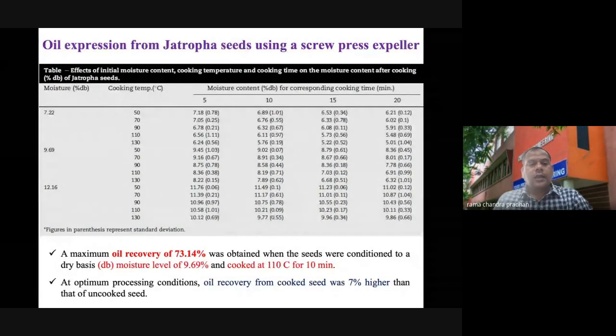So that is the optimum condition. With this optimum condition, oil recovery from the cooked seed was 7% higher than from the uncooked seed. Suppose you take uncooked seed at the same condition, 9.69% moisture content, without heat treatment, and go for oil separation using a screw-press oil expeller. Then you will get a 7% lower amount of oil. So for this seed, this is the optimum condition.